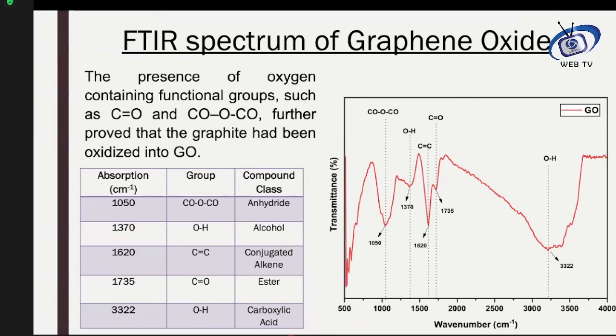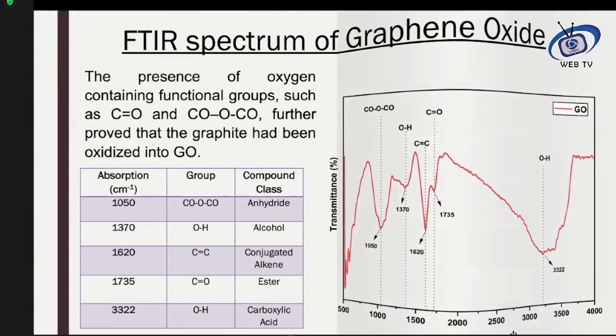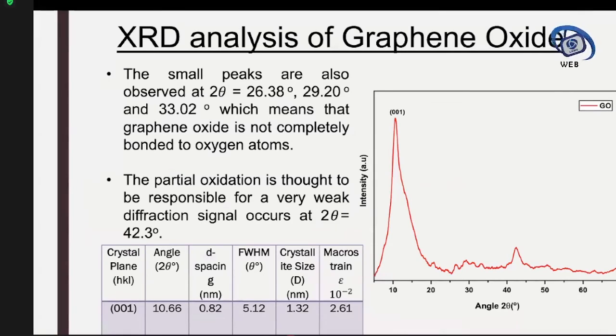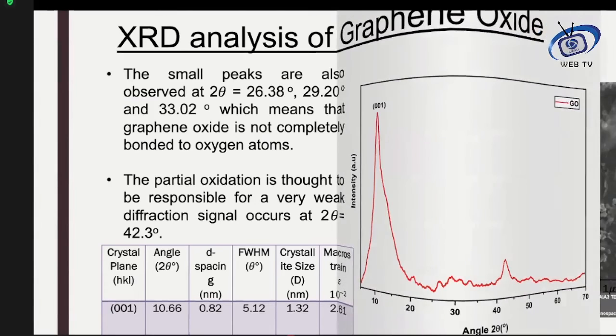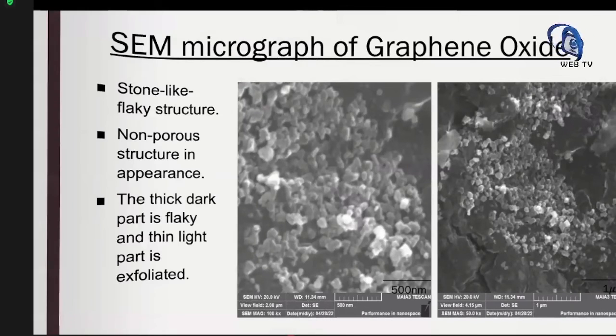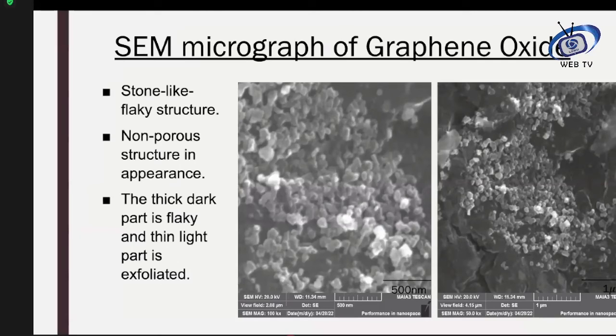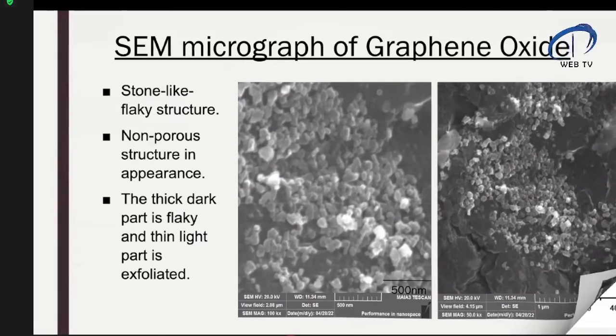The FTIR of the GO predicts the famous peaks, with the oxygen groups present in it. So the graphene oxide made there contains these characteristic peaks. XRD analysis also shows the 001 plane, which comes from the graphene oxide. This was an SEM micrograph of the fabricated graphene oxide, in the form of a stone-like flaky structure. The thick flakes represent the unexfoliated part, and the lighter ones represent the more exfoliated regions.